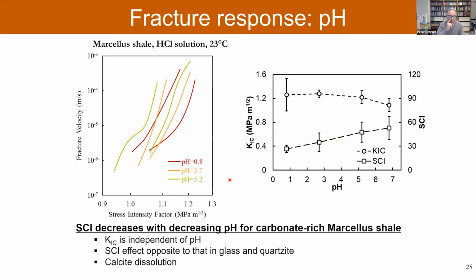And then I'm showing you one plot here for the change in pH. In this case, I'm showing this for the Marcellus, which is rich in carbonate. The upper curve here is for the fracture toughness. The lower curve is for the subcritical index. The fracture toughness is not affected by pH, but the subcritical index is. And if I go towards more acidic conditions, this rock gets weaker, right? It's easier to propagate the fracture.